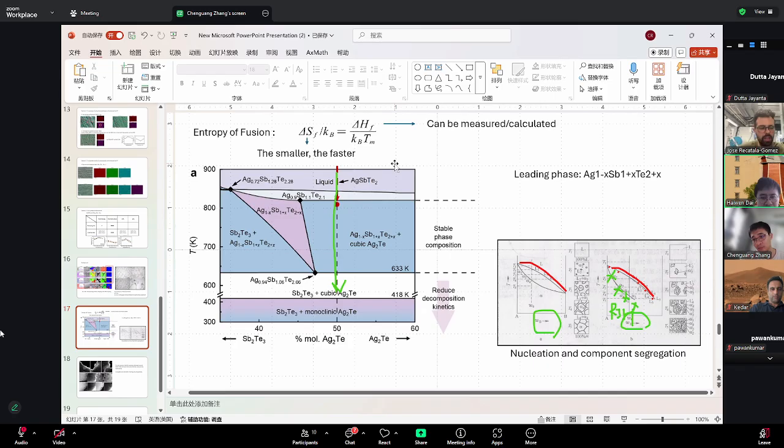Is there any possibility of a characteristic AST peak that is very far away from the Sb2Te3 peaks? Yes, but the antimony telluride peaks are overlapping. You can go ahead and look at our paper. I think supplementary figure 4 or something like that has some antimony telluride peaks, and you can see how they are really, really close. And that's for powder XRD. So powder XRD means polycrystalline materials, and you still have the resolution to separate them. You can see them, right?